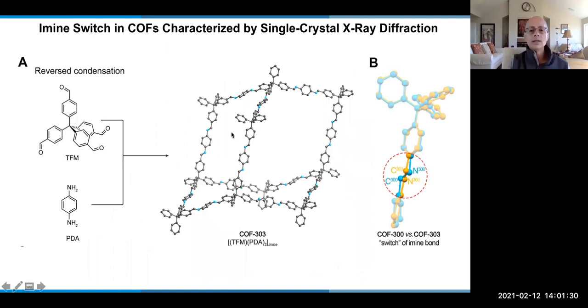Also, you can carry out this imine reaction by either having the aldehydes here or here. So you can have aldehydes here and amine here, or amines here and aldehyde here. The type of structure you make would have the possibility of having the carbon here or here. And with powder, you can't tell the difference. But with single crystal X-ray diffraction, we were able to tell the difference.